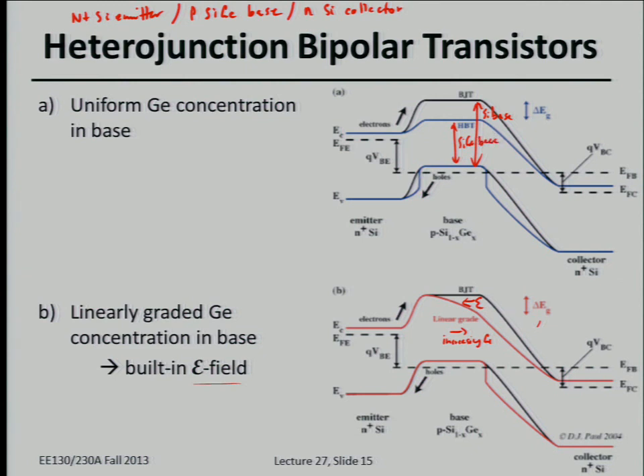So for the same applied voltage difference between the base and the emitter, you see this QVBE is the same for those two different cases. You can see the barrier for electron diffusion is lower for the heterojunction bipolar transistor, whereas the barrier for hole diffusion is the same for those two transistors. So basically you're making the barrier for diffusion lower for electrons than for holes. So you're favoring electrons going into the base. In other words, you're enhancing the emitter injection efficiency.